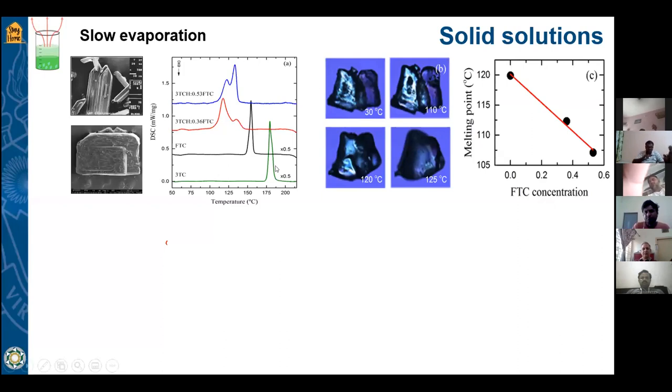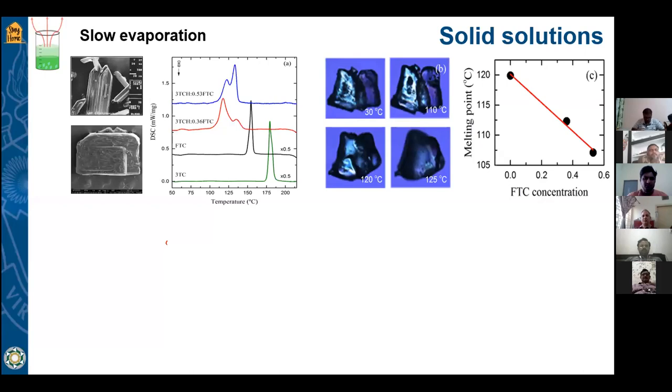Even if we are producing quite well and the production is quite consistent, during the slow evaporation process you don't have full control of the final stoichiometry, because it will be finally determined by the solubility. And we cannot guarantee that if we change the concentration, we will not have some residue of the raw material. So we want to have more control over the stoichiometry of the product.